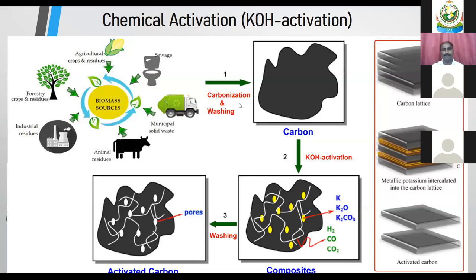That's why we need to mix it with the potassium hydroxide. After mixing, at a higher temperature, like 600 to 900 degrees centigrade, the potassium is evolved as potassium oxide and potassium carbonate. And sometimes during the heating treatment, the carbon evolves hydrogen gas, carbon monoxide, and carbon dioxide. So these gases are trapped. Finally, we get a composite-like material, and washing with concentrated HCl and hot water, we remove the potassium as potassium chloride, and finally we get the porous carbon. So this carbon is better than this carbon because it has a high surface area and high porosity. This porosity is basically for the sensing of molecules, and transporting the ions is much faster.